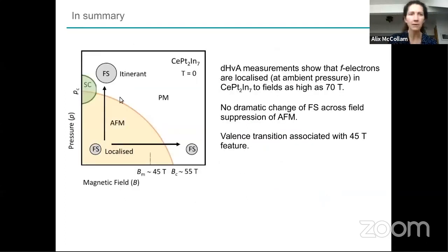All right, I took more than 5 minutes of the questions. Just to summarize, I show this picture again, and it's changed now. The original picture I showed you was large and small here at this 45 Tesla transition, but I think we've shown at least from 25 Tesla that we have a small Fermi surface with localized f-electrons that continues to be like that all of the way up to 70 Tesla. So we don't know that the critical field is around 55 Tesla. This was an extrapolated point that we imagined it should be about there, based on the type of behavior that we see in other members of this family.